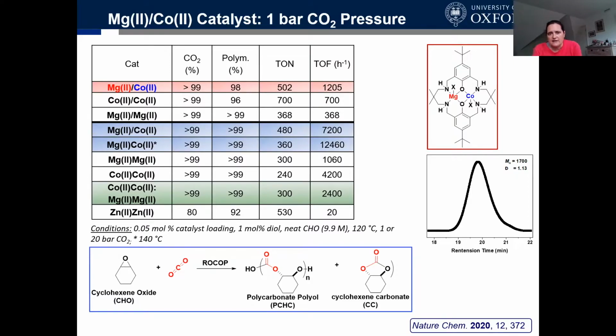But why do we get this enhancement when we run under higher pressure? This is actually an important question, because it isn't that the catalyst has a pressure dependence in its rate law. It's rather relating to the ability to efficiently stir the polymerizations. When we're able to do so, we get out of diffusion controlled regimes. In the pressurized reactors, we have very good stainless steel impellers that really improve the mixing of reagents. Underneath the two blue entries, we see magnesium and cobalt under the same conditions with the good stirring. Again, we have some activity jump for them, but once we're into these regimes where there is no viscosity limitation, you can see that this heterodinuclear catalyst, the magnesium cobalt one, always outperforms either the magnesium or the cobalt under any of the conditions.